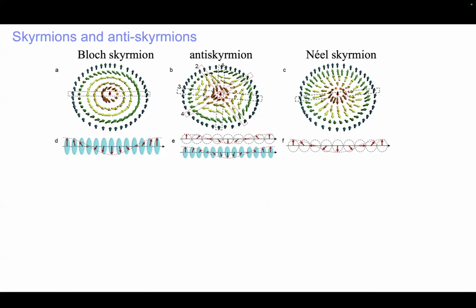And you can see them here. These are basically in a magnetic system which typically has perpendicular magnetization, an anisotropy direction. Then it turns out, instead of forming a uniform magnetic structure, under some temperature and field regimes the structure will automatically form an arrangement of small nanoscopic objects, which are typically circular, in which the boundary has a chiral structure stabilized by this chiral Dzyaloshinskii-Moriya interaction, which lowers the energy of the system.